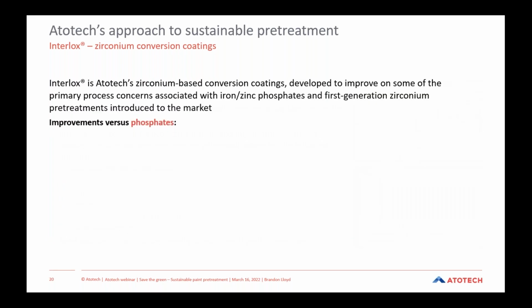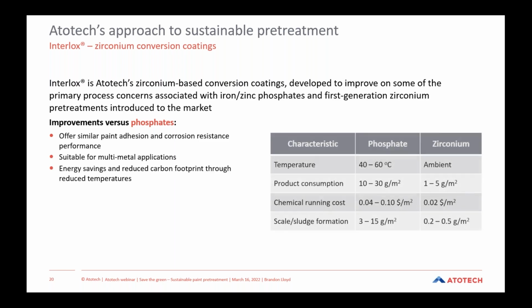So if we look at the primary benefits that can be improved on with Interlox in comparison to traditional phosphate-based pretreatments, those include the fact that they can offer a similar paint adhesion and corrosion resistance performance. They, again, are suitable for multi-metal applications. They can offer energy savings and reduce carbon footprint through the reduced operating temperatures. And on the right side of the page here, you can see a table exhibiting some of the traditional process parameters associated with a phosphate versus our Interlox processes.